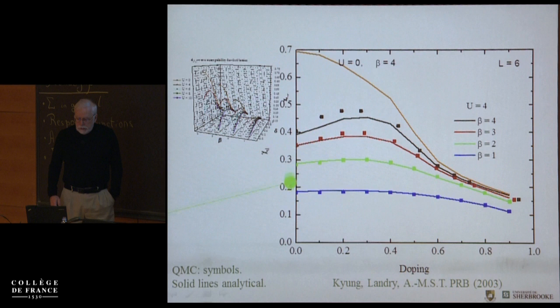This is the d-wave superconducting susceptibility. So it's in the particle-particle channel as a function of doping. This is for U equals 4, and the system size is not large, but it turns out that these are very high temperature and there's no size dependence. Beta equals 1, 2, 3, 4. And you see the TPSC is the solid line, and the quantum Monte Carlo are the symbols.